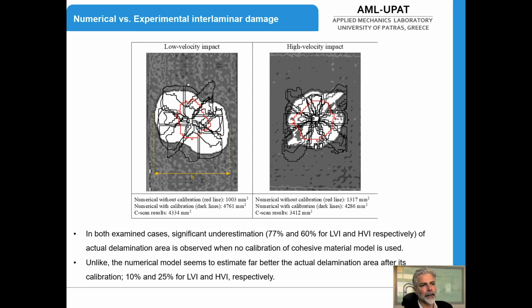This deviation is related to some of the assumptions made. The most important assumption is in the results that we have used in the case of Mode 2 experiments. Based on the experimental setup, we consider the pre-cracked specimen and not the non-pre-cracked specimen, because in our case we used the AITM, the Airbus experimental setup, and this is based on pre-cracked Mode 2 specimens.